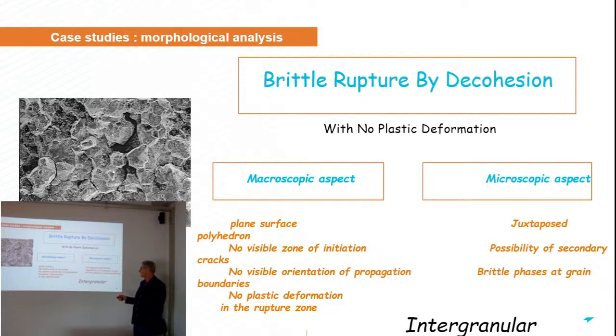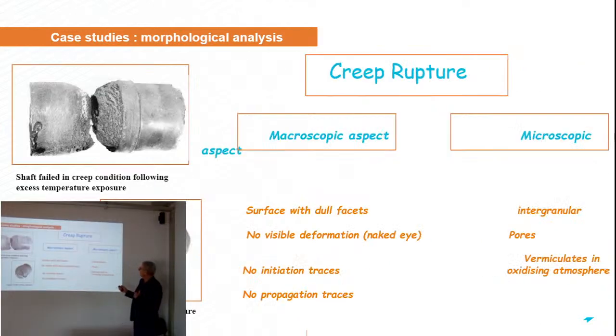You have a plane surface, no initiation zone, no propagation, and you can see at the microscopic level juxtaposed polyhedrons here, possibility of secondary cracks, as you can see here, for example, or here, and possibly brittle phases at grain boundary. Creep fracture, so you have surfaces with dull facets, no visible deformation, at least no initiation traces, no propagation. You can see here an example of this kind of fracture.